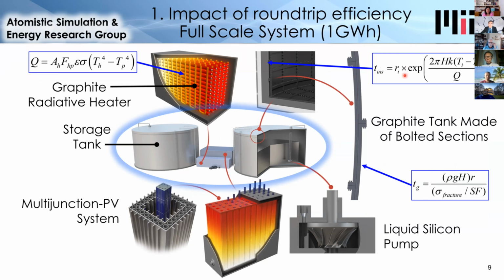And then for the insulation thickness, we looked at how thick the insulation needs to be based on its thermal conductivity and the amount of heat you want to lose per day. And so there's a trade-off here between the cost of insulation and the amount of energy loss. And so I left this heat flux as a variable and optimized it based on the overall cost of electricity output. This resulted in a heat loss of about 1% per day when you're storing for about a day. So 24 hours of storage, you would tolerate or ideally have 1% of heat loss per day. And this results in insulation about 1.5 feet thick.